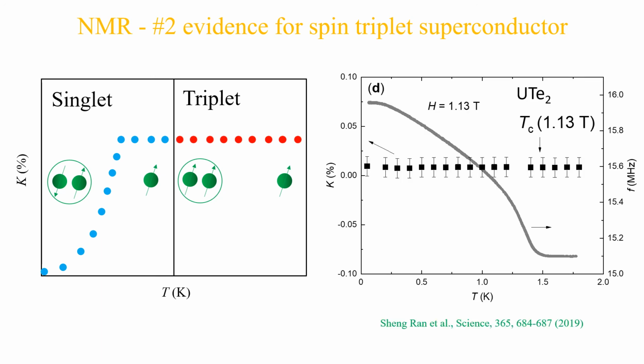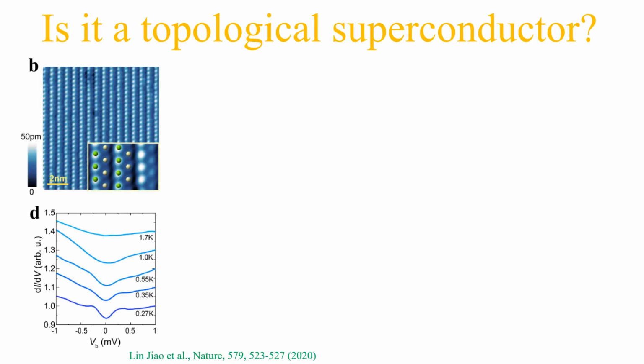When we did an NMR Knight shift measurement with a collaborator, this is how it looks. The spin shows no change as a function of temperature. It's a spin triplet pairing. Well, as I mentioned, spin triplet superconductor is a good candidate for topological superconductor. So, is this topological? To answer this question, our collaborator performed STM measurement.